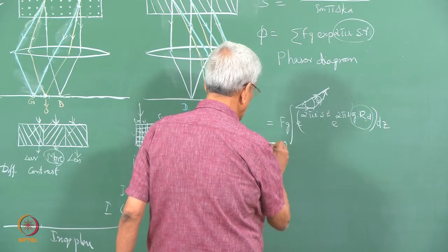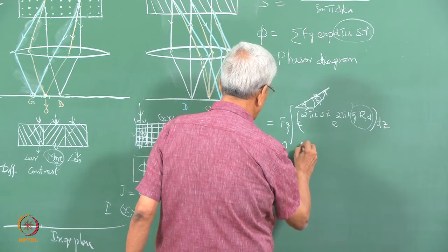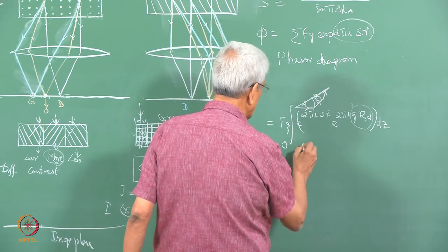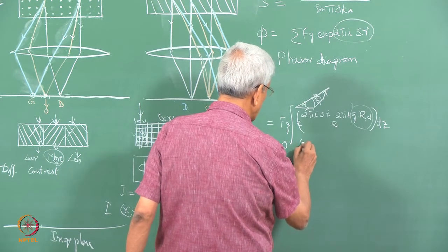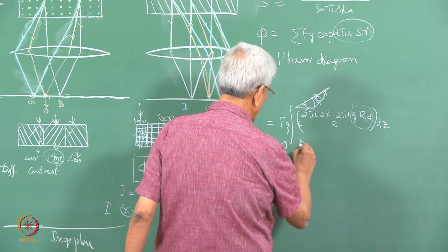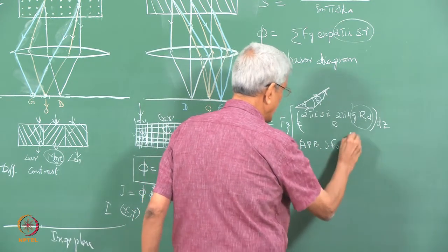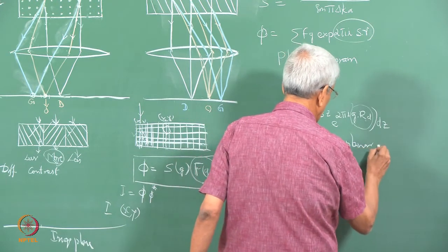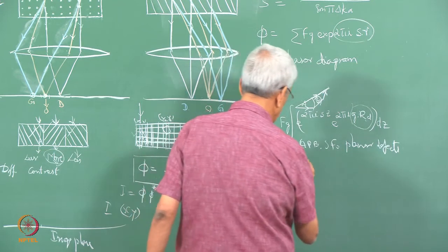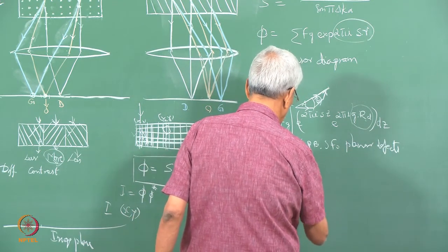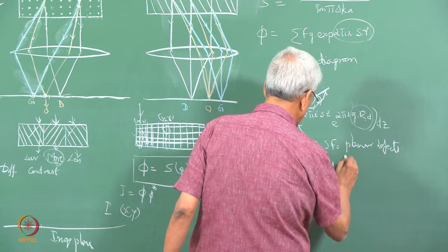This condition g dot R d equal to 0 can be used to find out the defect vector R d for various types of defects like antiphase boundaries and stacking faults. These are all planar defects. Similarly, there are defects like dislocations, which give rise to strain contrast.